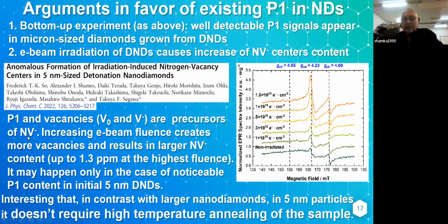P1 and vacancies are precursors of NV- centers. When we increase the E-beam fluence, we create more vacancies, and it results in larger NV- center content. In this case, we found that it is up to 1.3 ppm at the highest fluence. You can see the characteristic spectrum of NV- centers. But it may happen only in the case of noticeable P1 content in the initial 5 nanometer diamonds. They are there. Okay. By the way, it's very interesting that in contrast with larger nanodiamonds, in 5 nanometer particles, to create new NV- centers, it doesn't require high temperature annealing. It's an interesting fact.